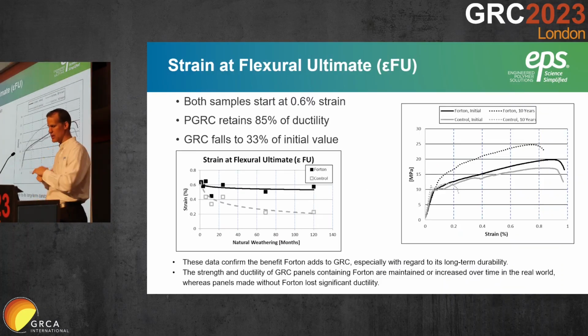And the strain at Flexural Ultimate, you can see basically with Forton it maintains a lot of its original ductility. After 10 years, you've got 85% of the ductility remaining when you're using the 5% Forton, and only about 33% of the initial value when you don't use Forton.